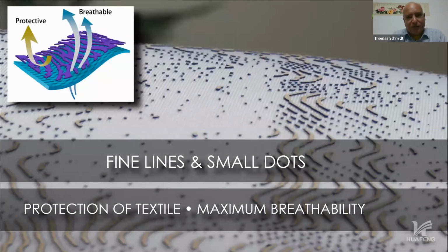But we are not limited to fully covered areas. We can also print very fine lines or very fine dots, and the bonding even of these very small dots is very, very strong, as they also cannot be scratched off. And these fine lines and fine dots fully guarantee the breathability of the textile material. So the textile is nearly as breathable as without coating, but still you can achieve very good protection of the mesh material by these lines and dots. And in addition, you can create very nice visual effects.